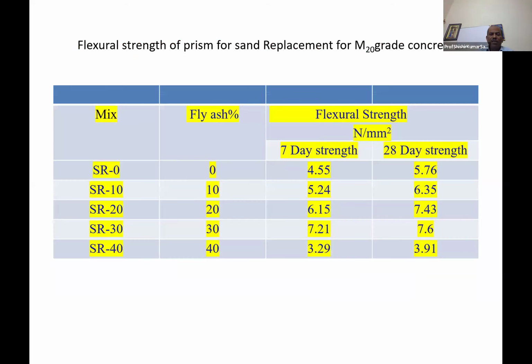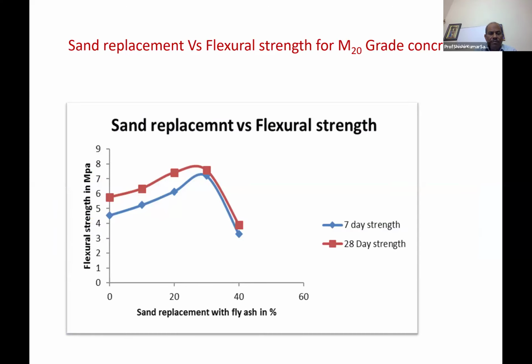Then flexural strength. Flexural strength requirement is minimum 4.5 or 5, so it is satisfying that way, 28-day strength. And you can see that in this case for 7 days, it goes on increasing up to SR 30%, but then decreases. 30% is the optimum in this case.